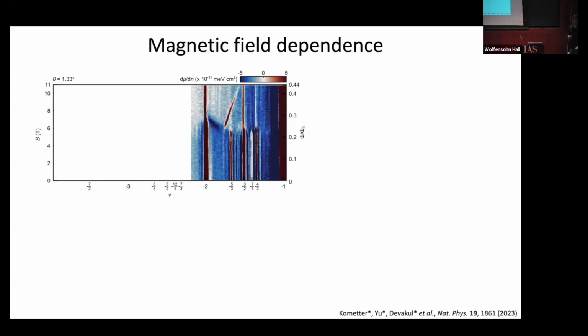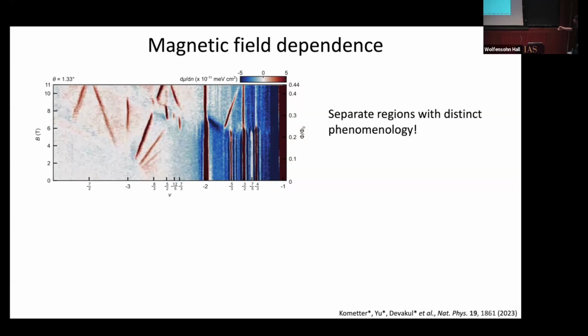But something interesting happens as you continue to tune the parameters. As you increase the magnetic field further, you find that there is some abrupt transition that happens over this entire range of filling, where the generalized Wigner crystals weaken, and there's something diagonal which starts to appear past a magnetic field of about 6 Tesla or so. So there's some broad transition, and then as you go even further out, as you dope even more to higher filling of carriers per Moiré unit cell, you can see that we're now dominated by these diagonal features. These are exactly the Hofstadter states that I described earlier. You can tell they have some non-zero Chern number because they're sloped, in contrast to the trivial states, which are the generalized Wigner crystals that I was talking about before.